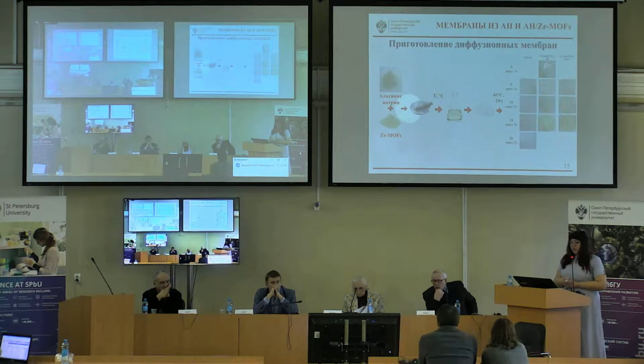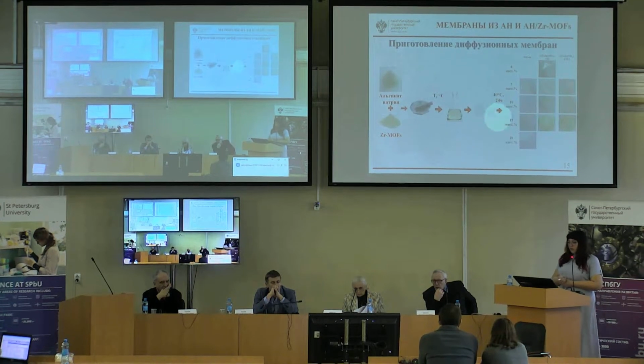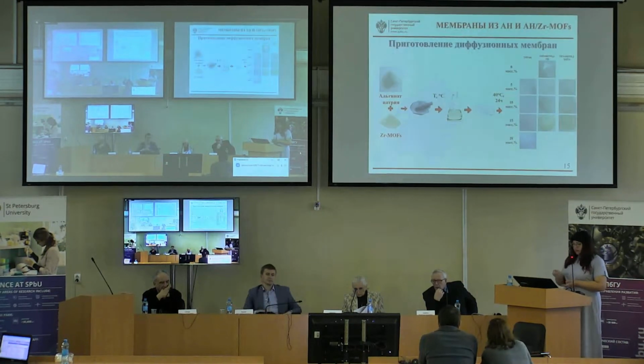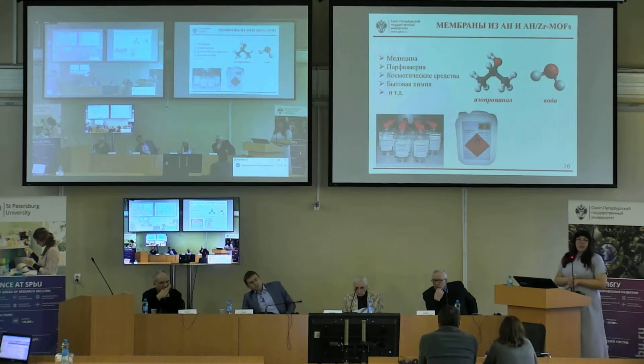MOFs were added to its matrix. Then the resulting mixture was dissolved in distilled water with further ultrasonic treatment. Diffusion membranes were obtained by pouring the resulting dispersion into a petri dish, followed by evaporation of the solvent.